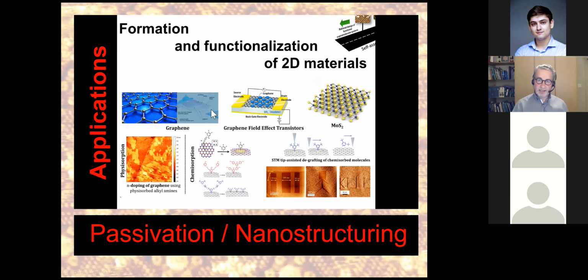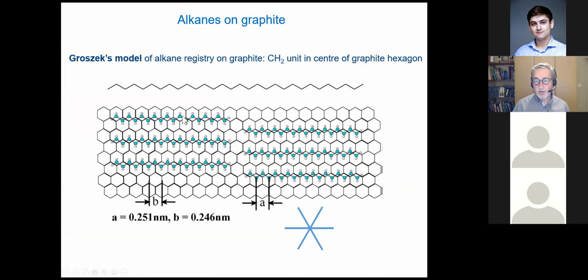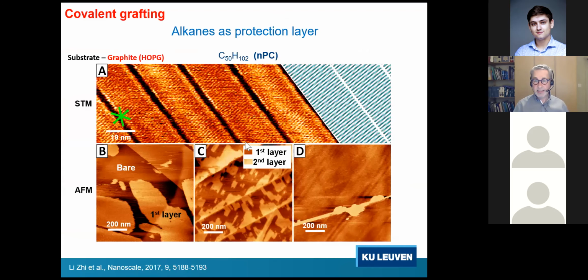Let me move on to another, maybe curiosity-driven application. Given that you have a substrate, a 2D material, can you protect that 2D material from reactive impurities or reagents in your solution or in your environment? We reasoned that covering the graphite in a monolayer fashion by long chain alkanes, because they form a high density network on the surface, could do the job. And indeed, this is a self-assembled monolayer of a long alkyl chain on graphite. This is one molecule here, and they stack in rows.